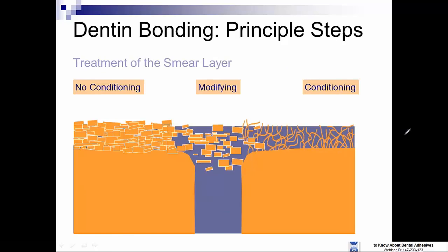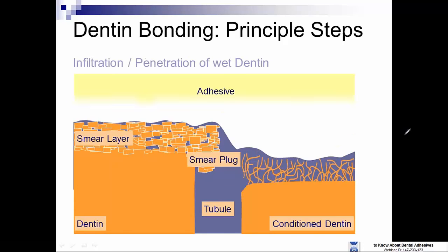Now, on the left-hand side, if we modify the smear layer, no conditioning or slightly modify it, this would be the way the smear layer is treated with self-etching adhesives. These are the adhesives that have acidic monomers in them that modify and slightly dissolve the smear layer while they're penetrating the tooth. On the right-hand side, what we're terming conditioning is actually acid etching. And in this particular case, we remove the smear layer completely when we rinse the phosphoric acid off the tooth, and we expose collagen represented by the little orange strings. We then will infiltrate the resin monomers from the adhesive in and around the collagen to completely surround it and penetrate the underlying dentin. This happens on the left-hand side of the screen with self-etching adhesives simultaneous to the slight solubilization or dissolution of the smear layer.